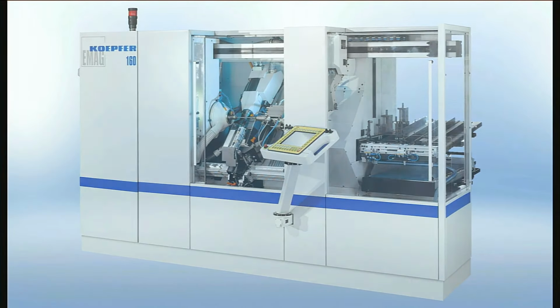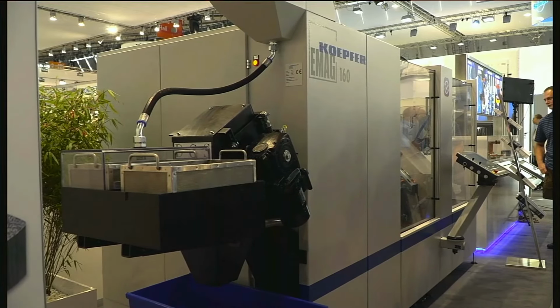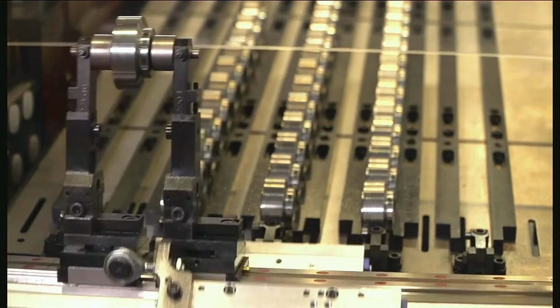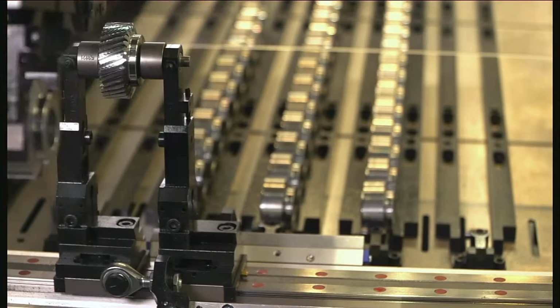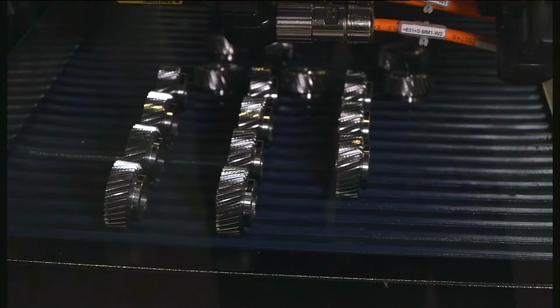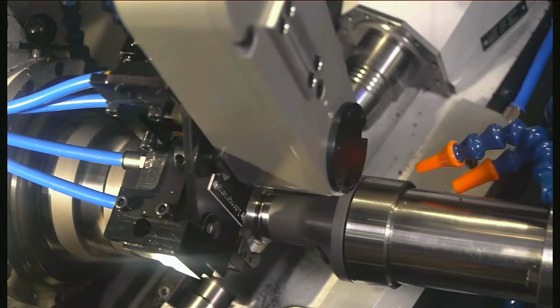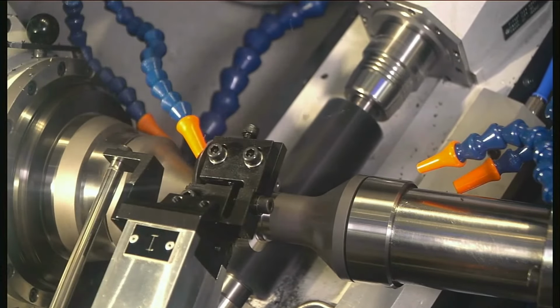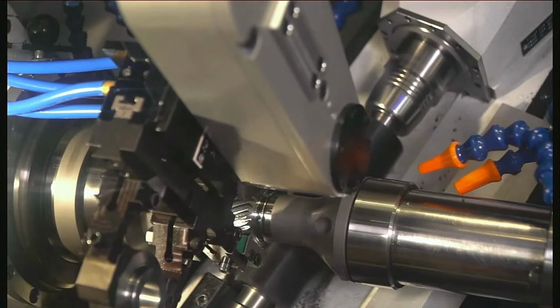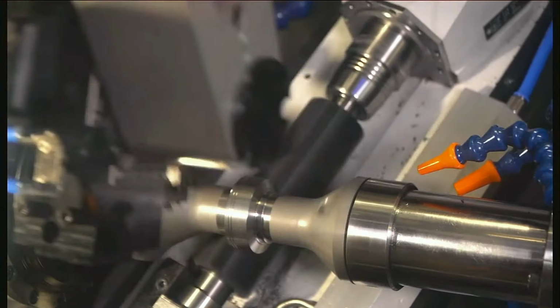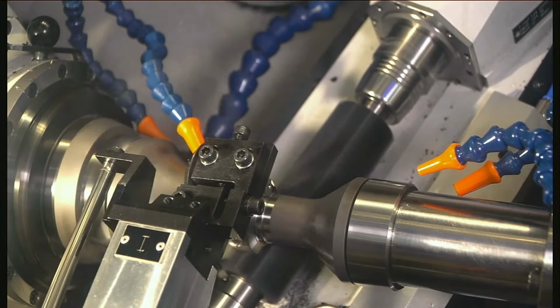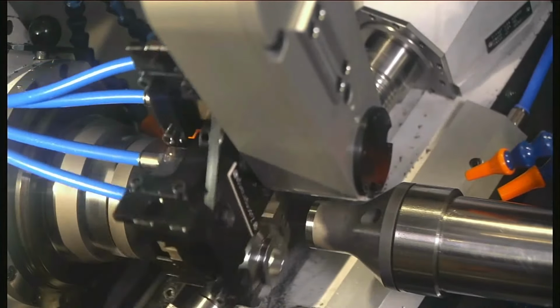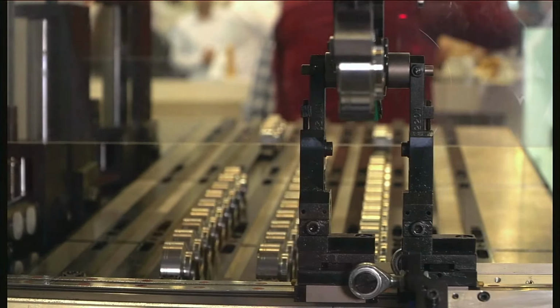So we see the 160 on the left side, the work area, on the right side, the automation cell. Here, this is in the area of the automation. We have a so-called servo distributor that takes care of the workpiece handling. The workpieces roll down a chute, they roll down by gravity, and the distributor presents the workpieces to our high-speed gantry loader. The gantry loader is equipped with a double rotary gripper, and this ensures chip-to-chip times less than 3 seconds, as you can see easily by means of this video. And you will see how we machine this workpiece with exactly the hob that we have determined earlier. It's a hob diameter 50, 2 starts, tungsten carbide with Alcrona coating.